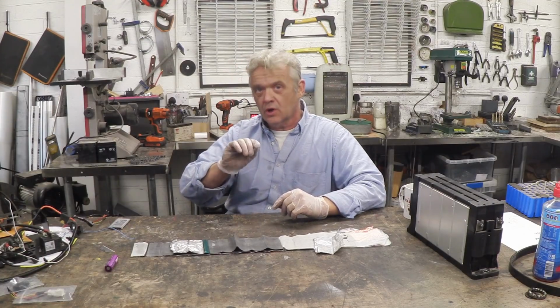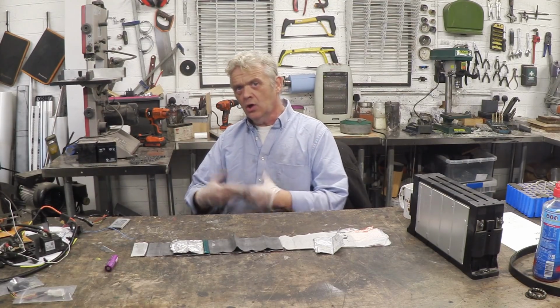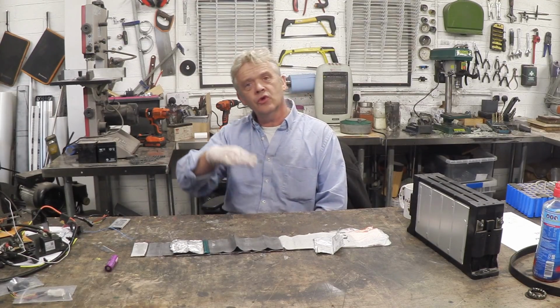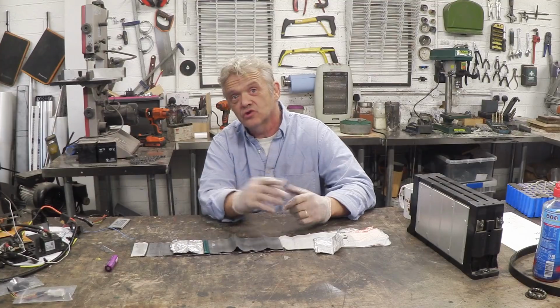There is a voltage at which you can't discharge them any lower, and if you go lower than that discharge voltage, then you will ruin the battery, because it will collapse. Now, that's a peculiarity of lithium, to be honest, and it is one of those reasons why you need a way of limiting that with a lithium battery. You can't overcharge them because they're basically full of petrol and there's a little bit of vaporization that goes on, and if you overcharge them, that vaporization gets to a runaway condition, and of course you get fires. So they can't be overcharged for that reason. They can't be left to drain too low or the galleries collapse. So there's a voltage in which lithium batteries can work, and outside of that voltage you either ruin them from over discharge or they'll just burst into flames.